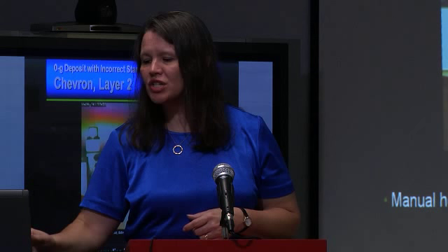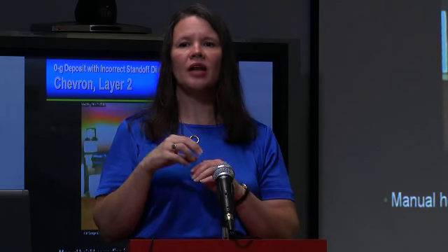Some people told us we were just going to build ball bearings. And so this is the next layer. Again, as we're a little too far away, you can see it pulling away. If you slow this down, you can probably make measurements on the shape of that molten ball at the end of the wire, and be able to do some measurements on contact angles and things like that to try to figure out exactly what your wetting forces are.